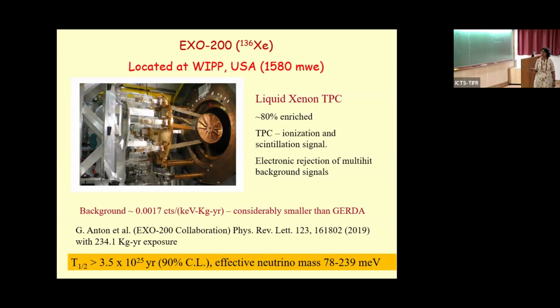Now you look at their background. It's at least an order of magnitude better. It's 0.0017. All the units remain the same. And this also has stopped running now. In 2019, they published the data with 234 kg year exposure, and they put a limit of 3.5 times 10 to the power 25 years, with an effective neutrino mass in about 80 to 240.